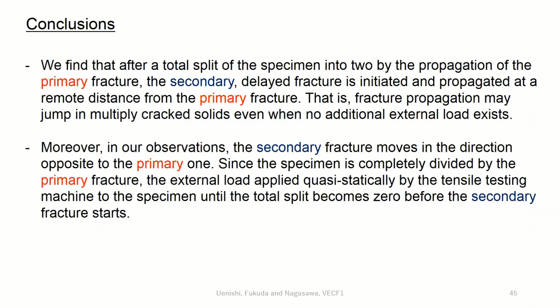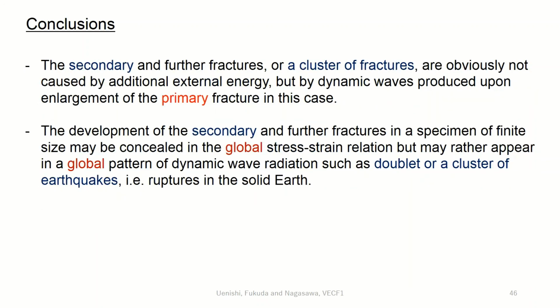Since the specimen is completely divided by the primary fracture, the external load applied quasi-statically by the tensile testing machine to the specimen becomes 0 before the secondary fracture starts. The secondary and further fractures, or a cluster of fractures, are obviously not caused by additional external energy, but by dynamic waves produced upon enlargement of the primary fracture in this case.